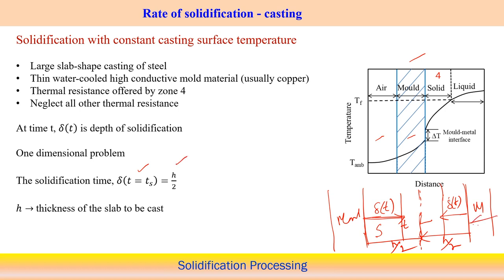because from both sides the heat loss will occur and the solidification front moves from both sides, and they come together at the middle point. So, if the thickness of the slab equals H, then it will be H by 2. So, H equals the thickness of the slab to be cast.